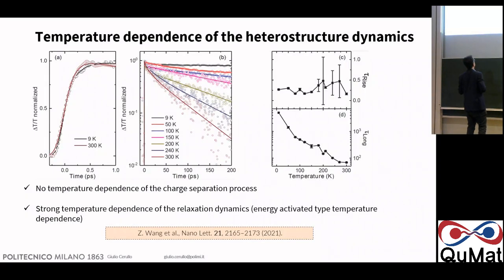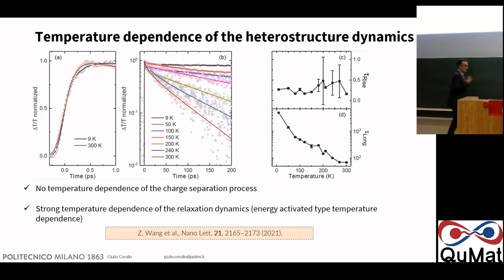Now, we can do this as a function of temperature from 9 Kelvin to room temperature, and we can see that the rise time is nearly constant on the order of 200 femtoseconds, while the decay time is strongly dependent on the temperature, and it goes from more than a nanosecond down to less than 100 picoseconds at room temperature. So this shows that there is an energy activated type temperature dependence for the relaxation time, while there is no temperature dependence for the charge separation.